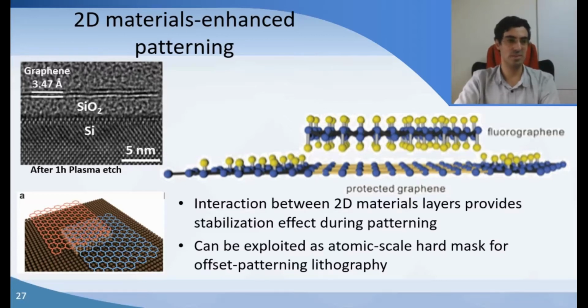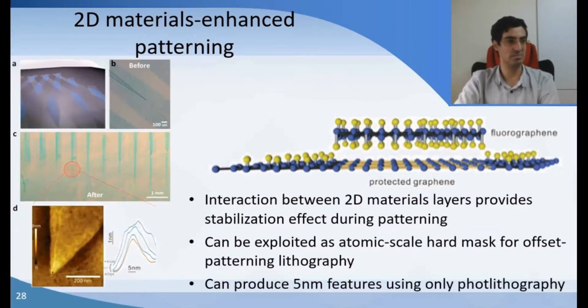So we find that we can stabilize both the fluorographene top layer and the pristine graphene bottom layer if they're underneath one another. And so we use that as a hard mask. And a hard mask means that we can now use graphene as a protecting layer for the silicon underneath. Not just silicon, but any kind of material underneath. And so regions that have double layers of graphene would be protected during dry etching, whereas regions that have only a single layer would get removed. And so we show that before, you have these two layers of graphene, and afterwards only the bilayers remain. And so the features that are covered by both of them could have very sharp corners.